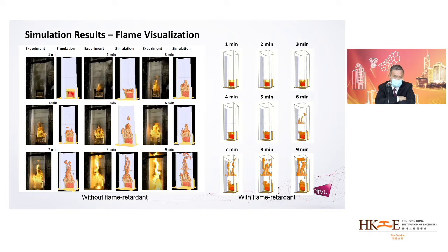And having got very good agreement, we can confirm that this multi-scale approach is very useful, and therefore we move on to the right-hand side to look at the facade material with the flame retardant. And we can see that although we do not yet have the experimental result, from the result, the spread from lower panel to the upper panel is literally 9 minutes instead of 6 minutes, because this is a flame retardant material. So effectively we can capture the characteristic of flame retardant using kinetics that we obtain from a separate bench type experiment, and then input and inform our CFD calculation to do a very effective calculation, even for flame retardant materials.